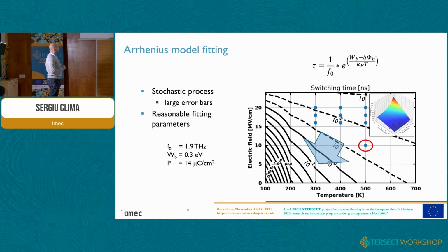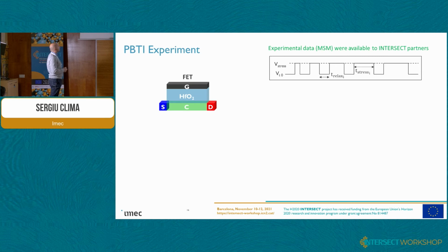And that's why we have to extrapolate, fit the Arrhenius, and extrapolate what happens at those lower fields and lower temperatures. So my colleagues took some measurements on FeFET by doing some stress and measurements on the ferroelectrics.